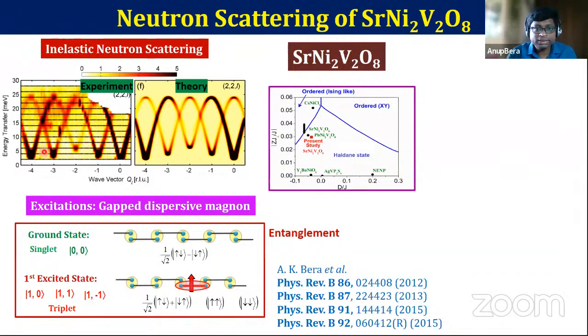Now we measure the excitation by neutron inelastic scattering experiment, which is shown here. And this is the theory, which is the excitation pattern calculated theoretically, which shows there is a presence of an energy gap. This is called the Haldane gap, and it protects the system from ordering magnetically. And there is nice matching. And how we can understand this behavior is that the ground state is somehow forming this kind of singlet state, or that is called the valence bond solid state, where the spin 1 quantity of nickel 2+ is decomposed into two spin half quantities, and which is entangled with the next nearest neighbor spin. And this is a very entangled state.